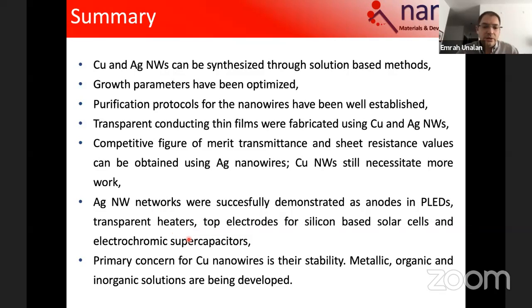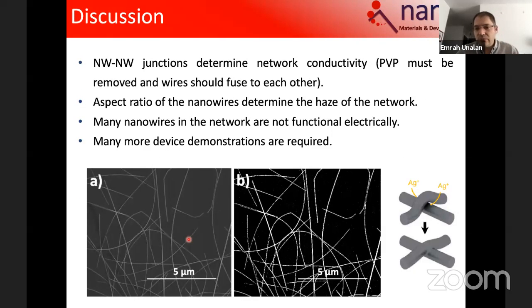And with this, I would like to spend some time on this discussion slide, on what we have done and what needs to be done further. So you literally have sticks of a conducting material, and you disperse the sticks on a flat surface, right? So the nanowire junctions are determining the conductivity, because the nanowires themselves are perfect conductors. Other than the surface, I don't have any defect to scatter electrons while they travel.